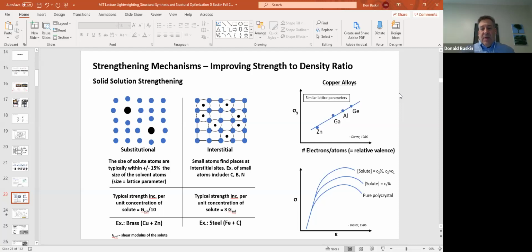So the material is primarily made out of copper, and then you substitute some of the copper atoms with zinc. That's an example of a substitutional solid solution strengthened alloy. With interstitial solid solution strengthening, like I said, you insert smaller atoms that have a smaller diameter in between the main lattice points. Some small atoms that do this are carbon, boron, and nitrogen, which are pretty small relative to, say, iron.